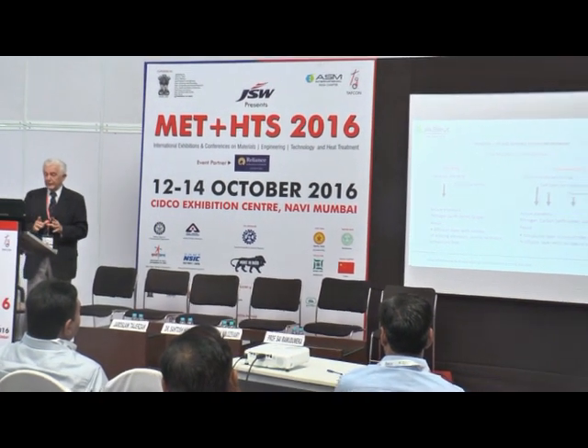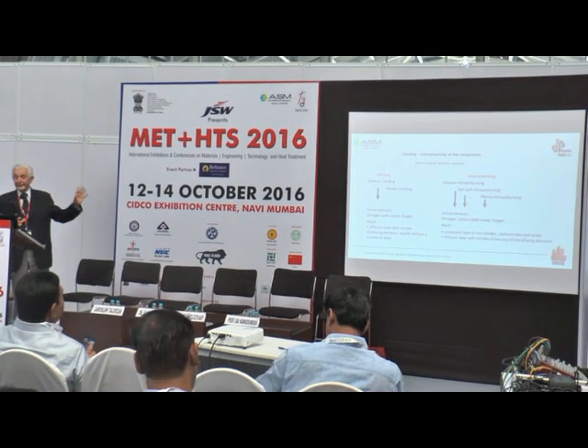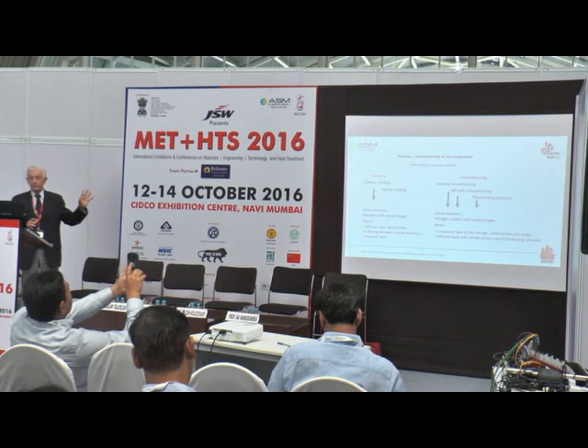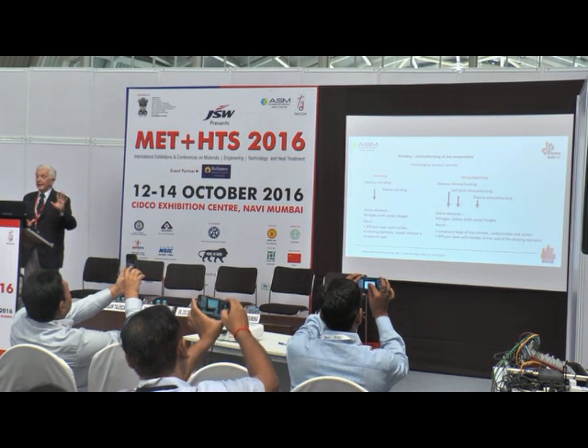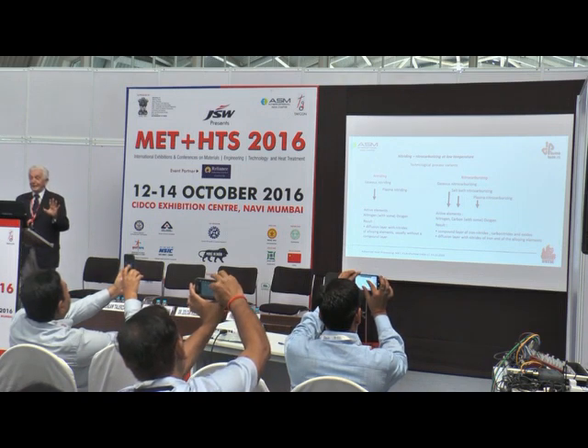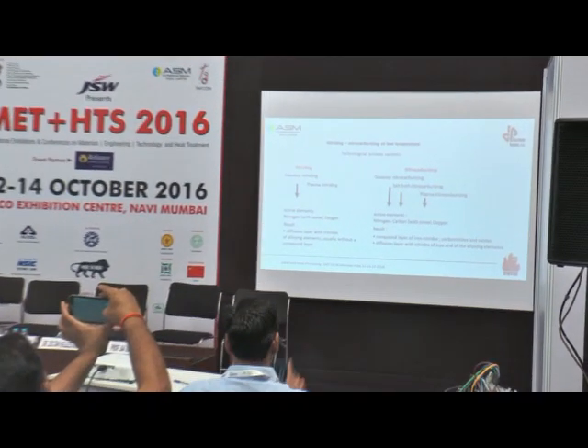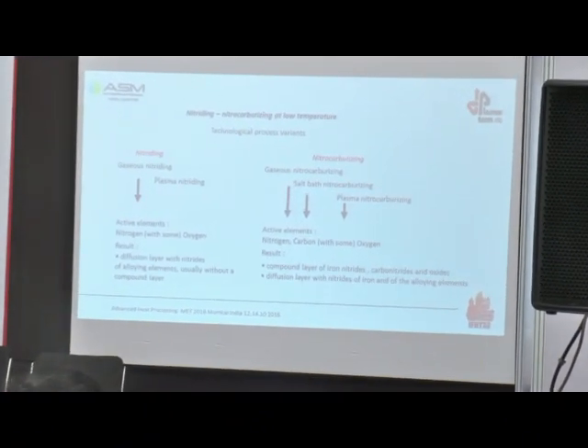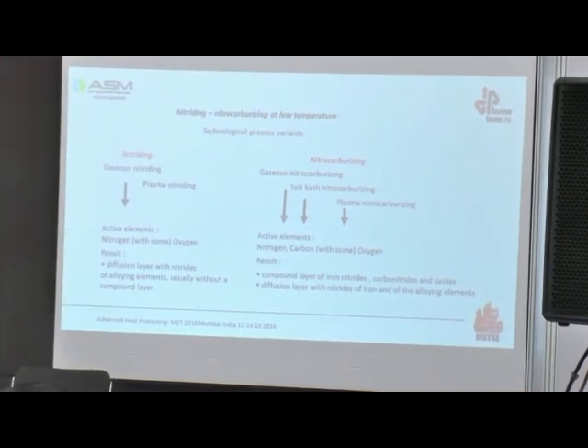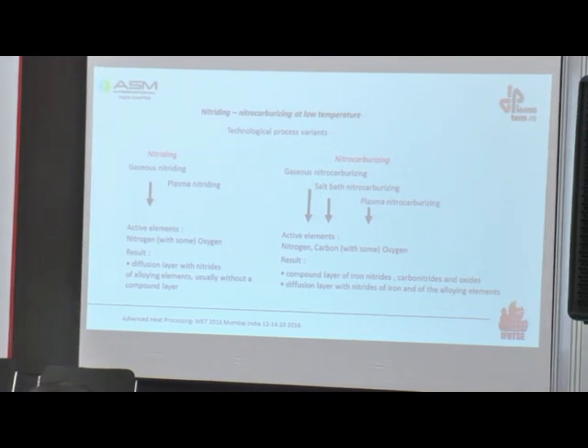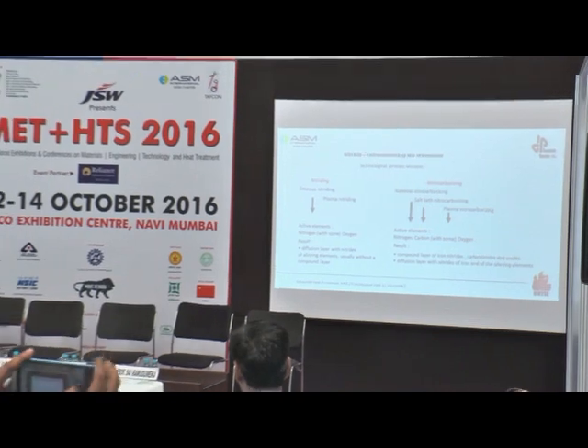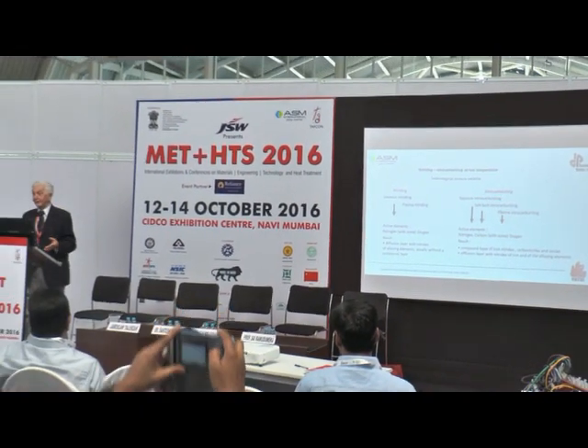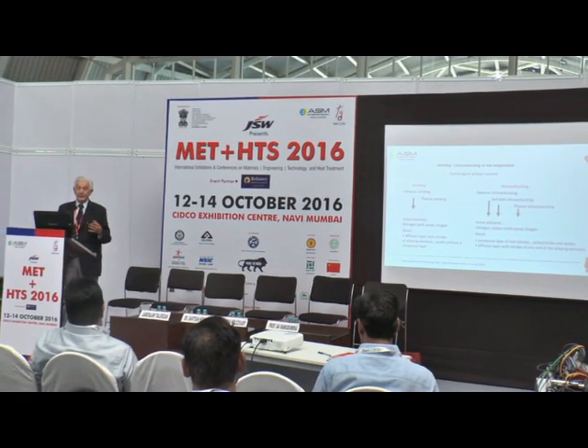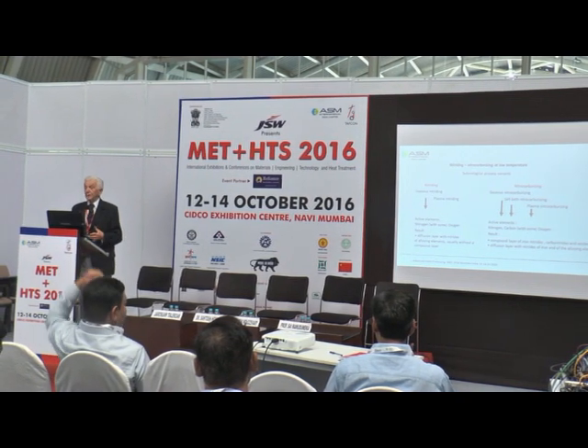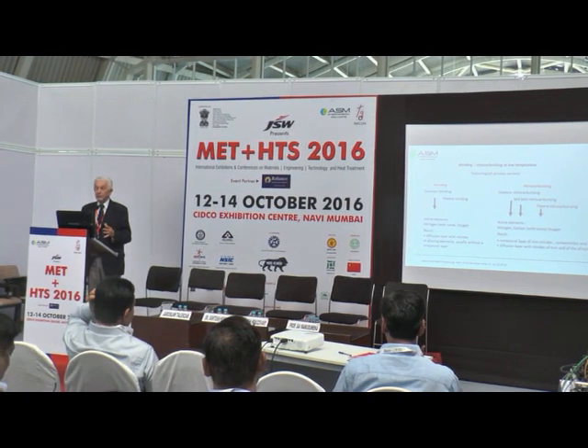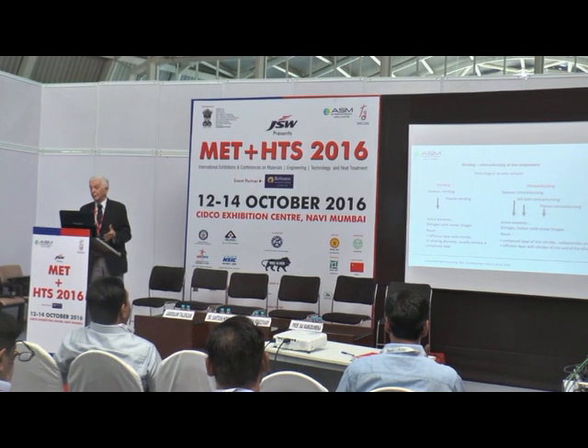So what I should like to emphasize very much is that when we talk about nitriding, we can talk about nitriding with just two different procedures: one is gases and the other is plasma. When we say liquid nitriding, that's not correct, because in salt baths we do not make nitriding, we make nitrocarburizing. This is very important, because many times in industrial applications there is this kind of confusion. So that's why I made this small presentation: nitriding is gases or plasma, and nitrocarburizing is gases, salt baths or plasma. I must tell you that I am very much a fan of salt bath nitrocarburizing, but unfortunately, due to the environmental regulations, we had to replace it with other procedures, gases or plasma, which certainly work and are very good, but still in many application areas salt bath has a big advantage, but we have to forget about it for the moment.